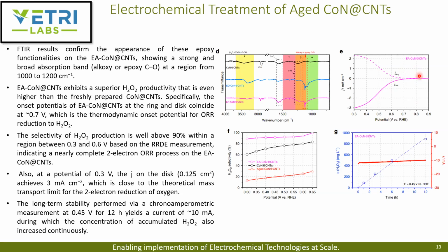As they did that, when the aged Co-N CNTs were subjected to the electrochemical activation, we can see that we were able to bring back the peroxide production. And now it's even at a higher selectivity. As we can see here, the selectivity was about 80%, and now they can improve the selectivity to about 90%, whereas for the aged one it was initially about 20%.